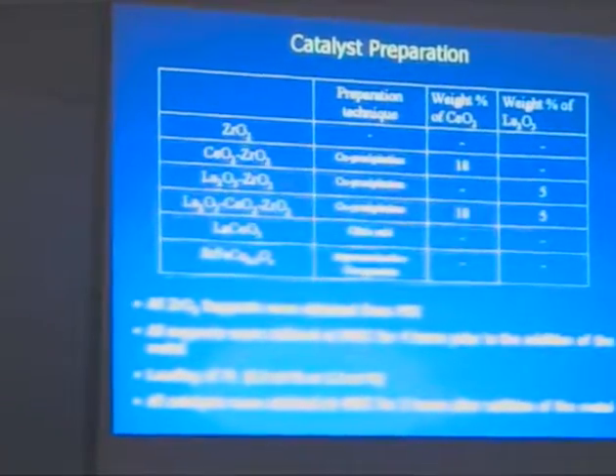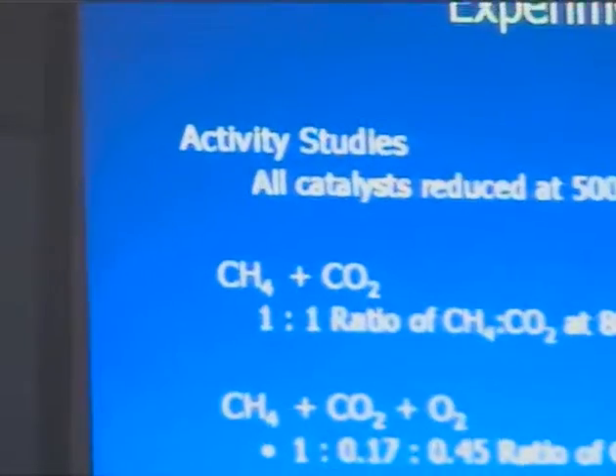All materials were calcined, all supports were calcined at 800 degrees C for 4 hours before the addition of the metal. We use loadings of platinum primarily of 0.5 weight %, and then we also have a 1.5 weight % platinum zirconia catalyst for comparison. And then we calcined all materials at 400 after the addition of the metal. For our activity studies, all of the catalysts were reduced at 500 degrees prior to reaction.